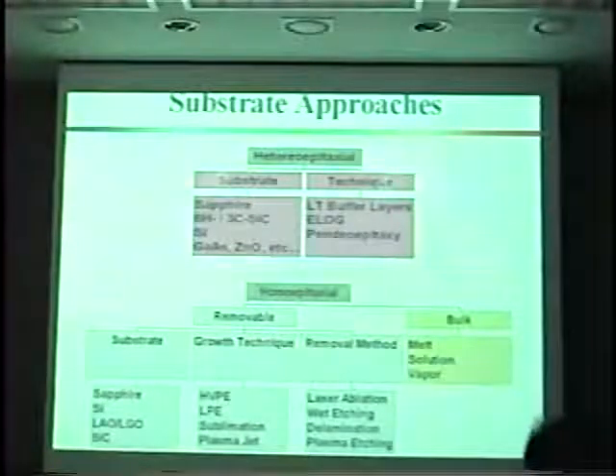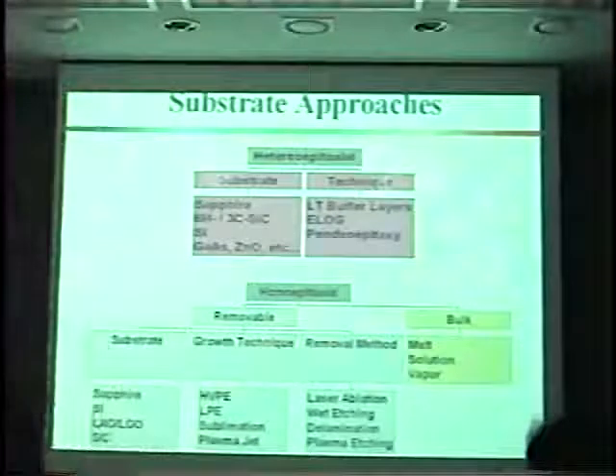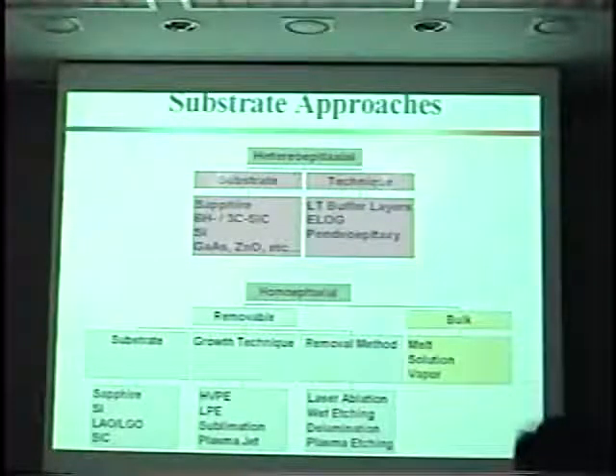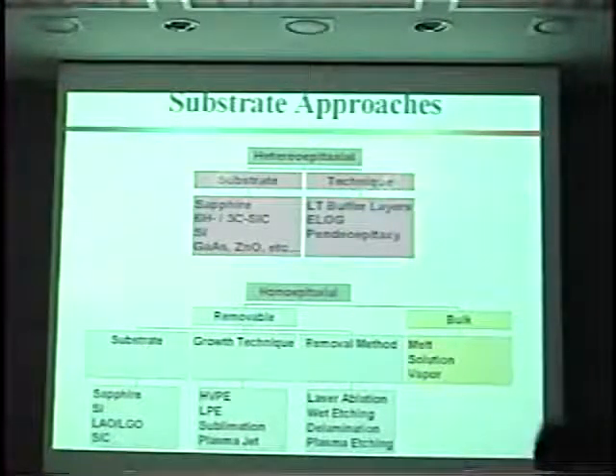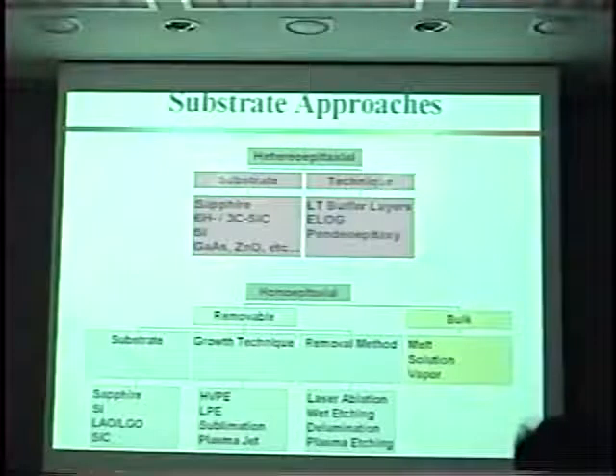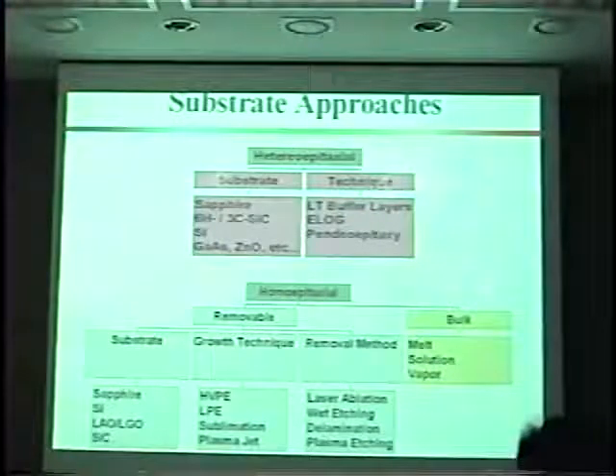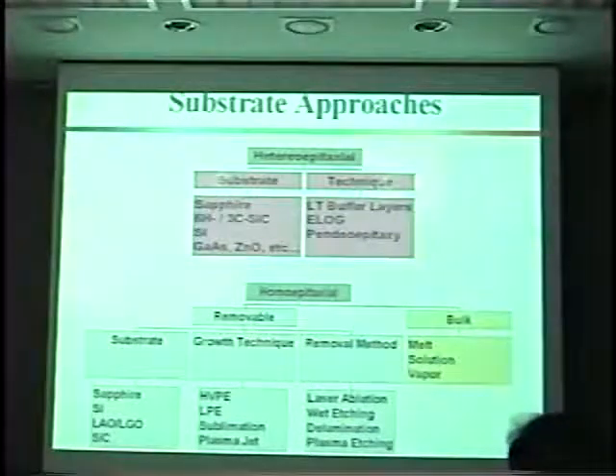But there still is not a good substrate for gallium nitride. No one has yet successfully grown large area bulk gallium nitride on a routine basis at low cost, as we have with silicon or gallium arsenide, for example. So there are basically 2 approaches, 2 general classes that one might take. One is to take an existing substrate, so sapphire is most common, silicon carbide. People have also investigated silicon, gallium arsenide, zinc oxide, a variety of other substrates, and just grow heteroepitaxially on the mismatched substrate. And that's currently what we are doing in the commercial applications.